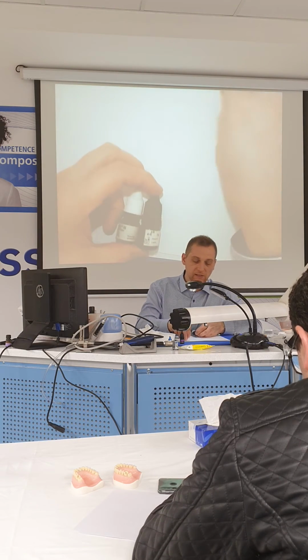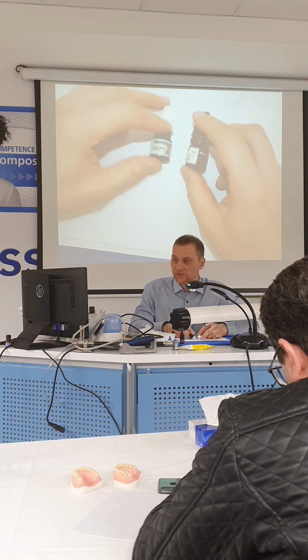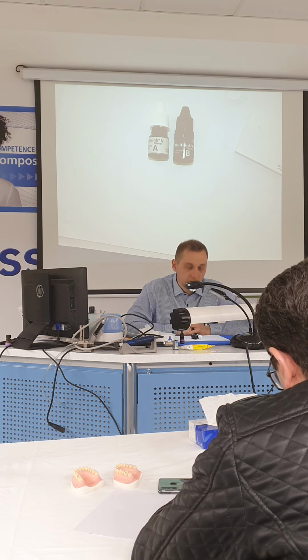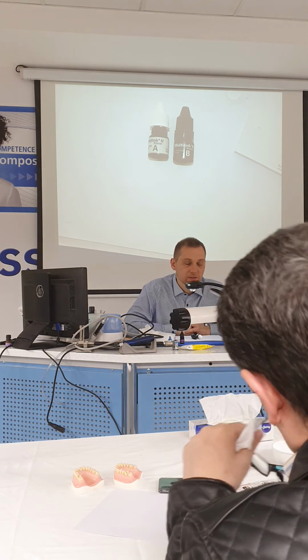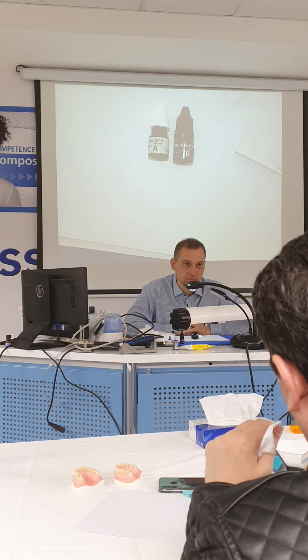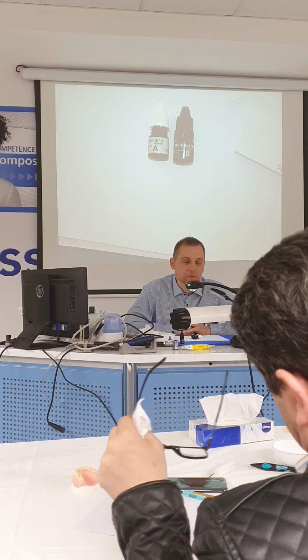Okay. I have another question. When we do tooth preparation, when we do an inlay, we use the Multilink primer for the tooth. Why didn't we use it for the veneer or for the crown? Because of several reasons. The first reason is that this primer, which is used together with Multilink N, is purely self-etching. You cannot use it in combination with phosphoric acid. That's why you cannot guarantee that you will get very good bonding strength to enamel.